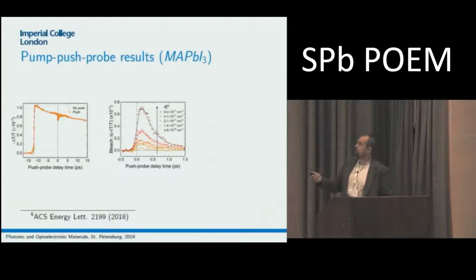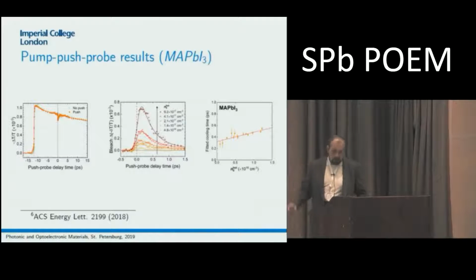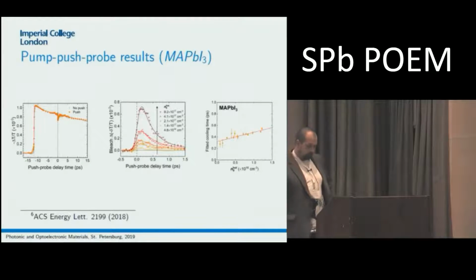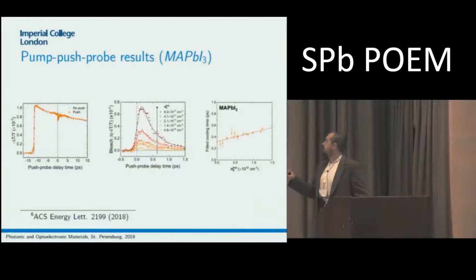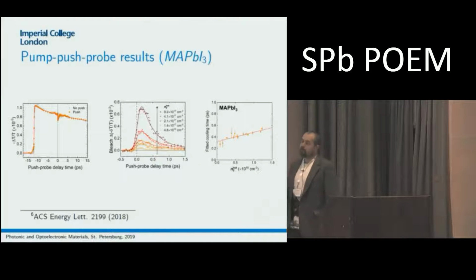And what we have noticed is that the more hot carriers we have, the longer they take to cool down. These are the times. It's a sub-picosecond process. At lower push intensities, it's between 100 and 300 femtoseconds, but at higher push intensities, it goes up to maybe even 1 picosecond. So we did thorough 2D scans, changing the power of the pump radiation and changing the power of the push,